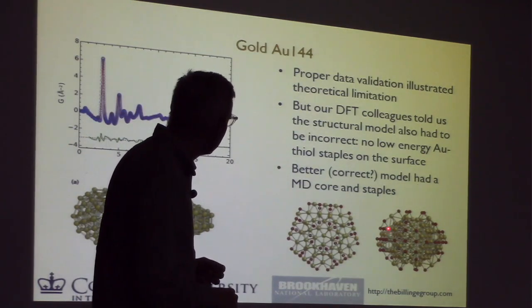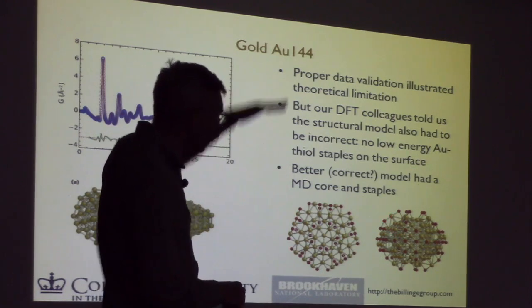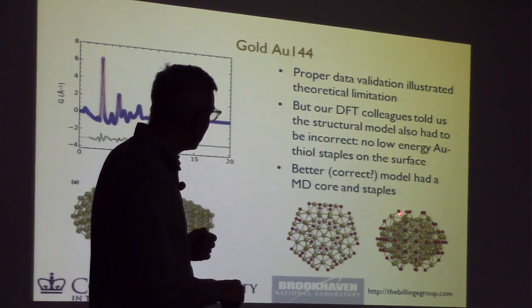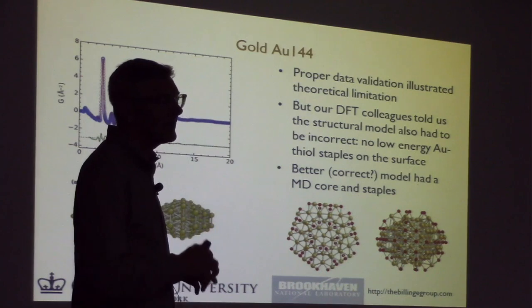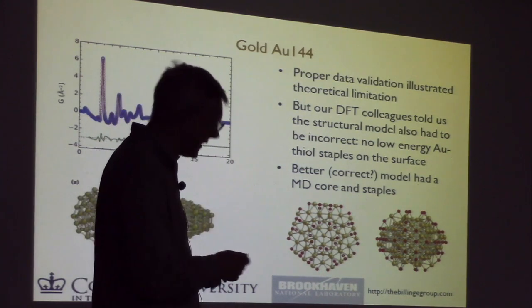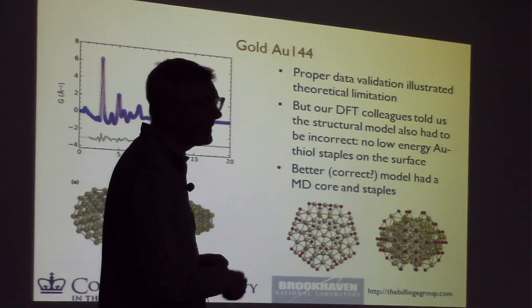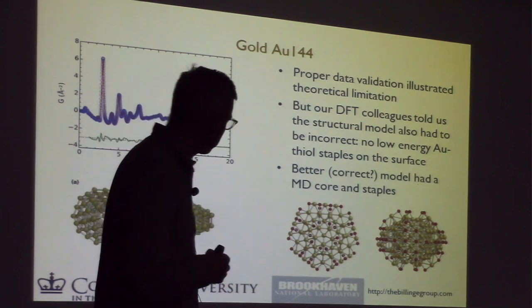So they look like this. You can kind of see one here. This red is a sulfur. These are sulfurs, and that's a gold. So there's a gold on the core. It goes up to sulfur, across to this gold, which is hanging out at the side. Another sulfur and back down to gold. These are thiol staples. And these things are actually needed to energetically stabilize this object.